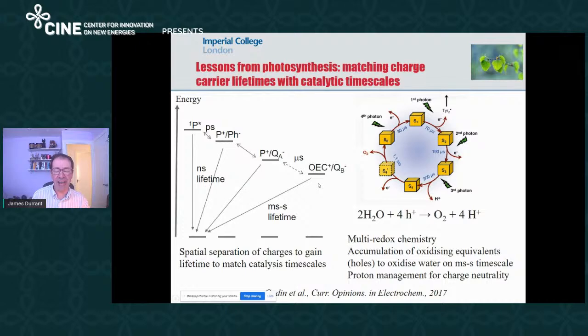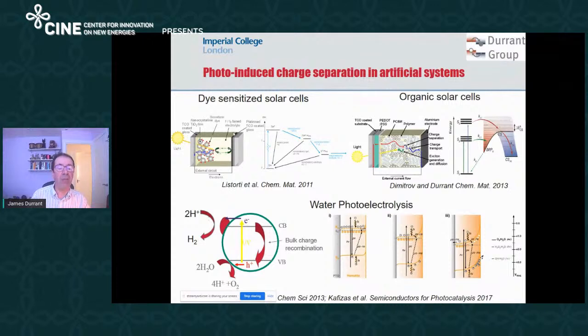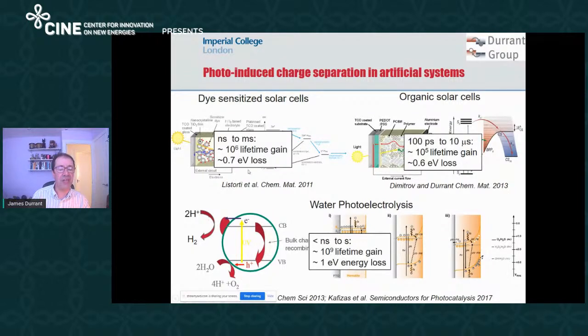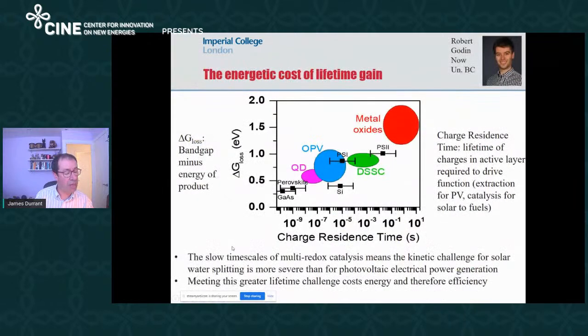And we've been trying to understand essentially that argument in many systems in my group over the last few years. This is just some examples both from dye-sensitized and organic solar cells and what I'll be talking about today, water photoelectrolysis. And in both cases, there's a large lifetime gain required. In solar cells, not to drive catalysis, but to drive the extraction of charge to the external circuit. In water photolysis, it should drive the catalysis. The lifetime gain is most challenging for the catalysis because it's so slow, and that correlates with the observation that these energy losses are the energy losses typical in the best devices. And you can see that water photoelectrolysis typically has a larger energy loss, and that's probably correlated with having a larger lifetime gain required to drive function.